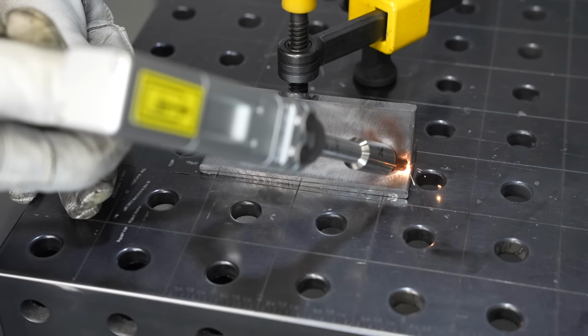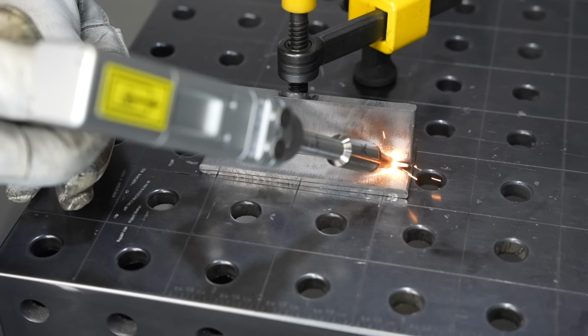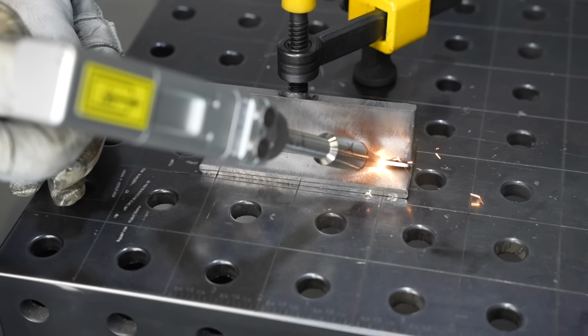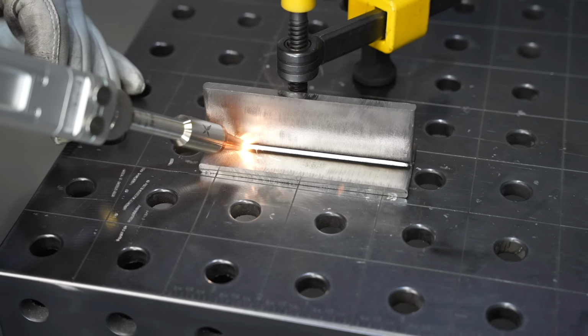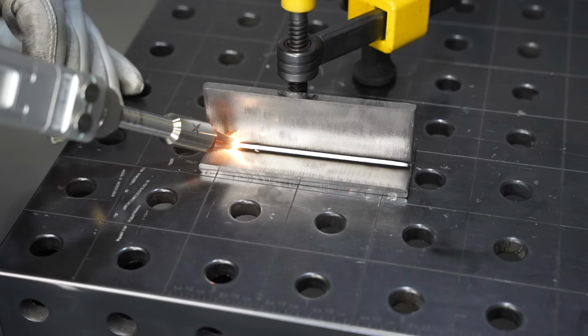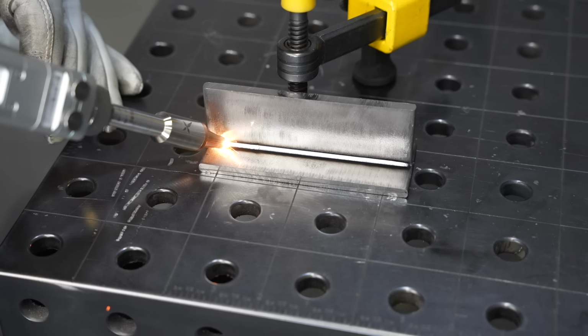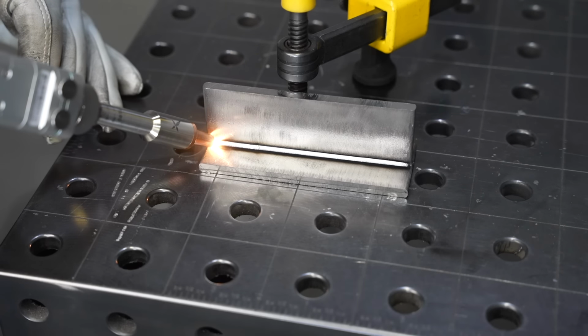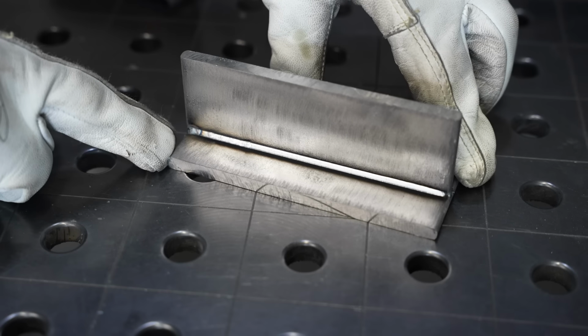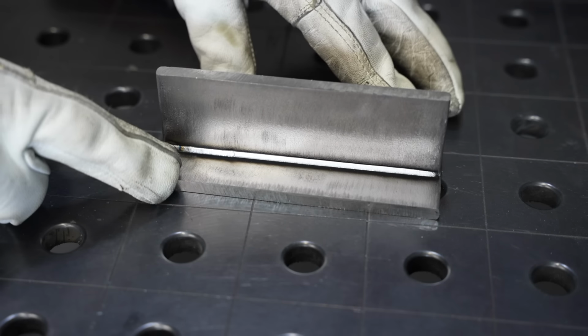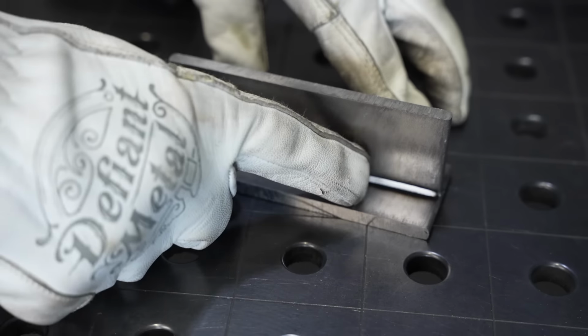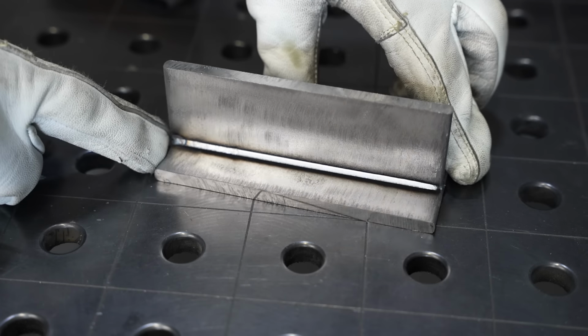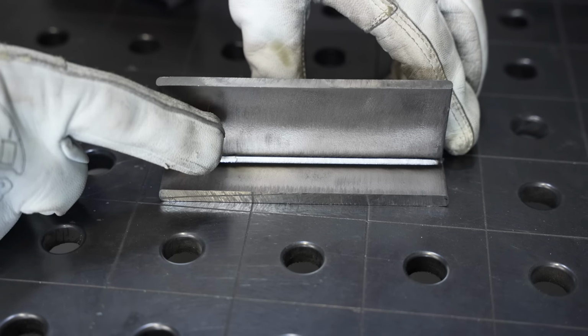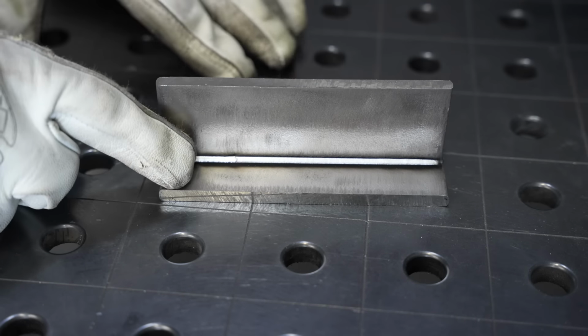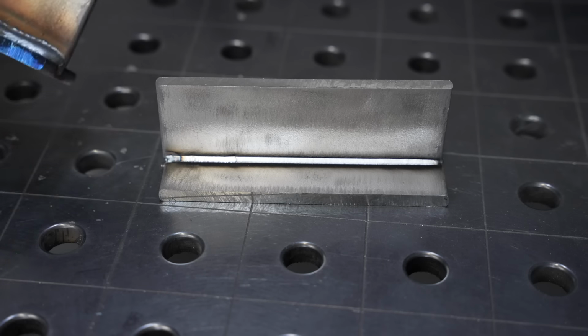Now I'm traveling even more slowly here, which is going to help to get even better penetration on this thicker plate, to do the best that we can, even though this is really pushing past the limits of what this machine was intended for. All right, well, here you go. I did not even know what to expect on 1/4 inch thick plate, but that turned out really good, really slick, but very, very small and probably not adequate for most structural situations.